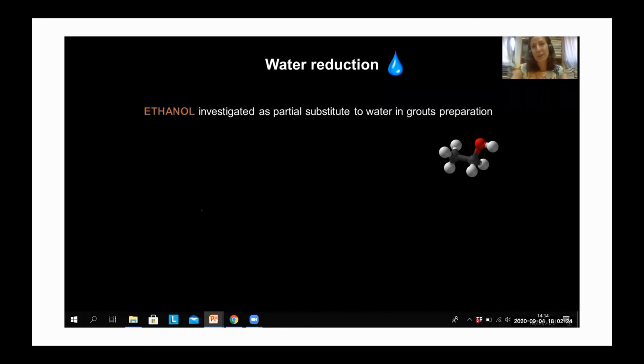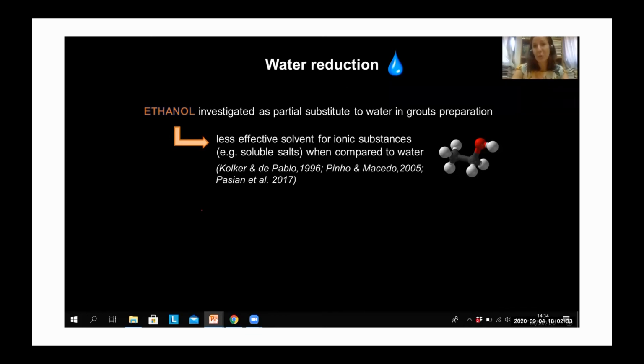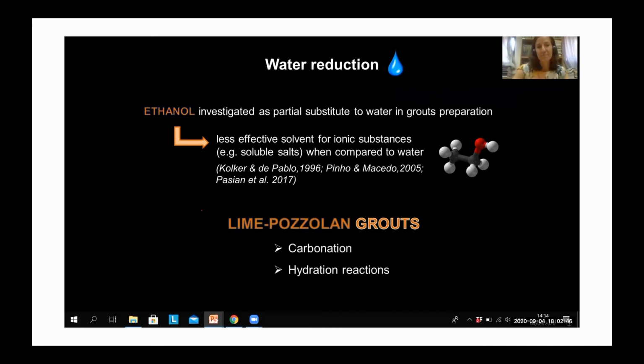So how was water reduction achieved? Ethanol, so alcohol, was investigated as a partial substitute for water during grout preparation. Why ethanol? Because it's a less effective solvent for ionic substances, so for soluble salts, in comparison to water, and that was studied in the past. During this research, lime pozzolan grouts were considered. We know that in a lime pozzolan material, two main reactions are involved, which are carbonation and hydration reactions. And so it needed to be understood what was the role of water in those.